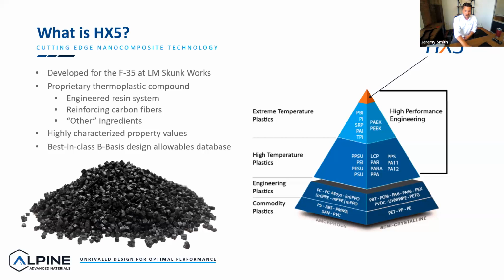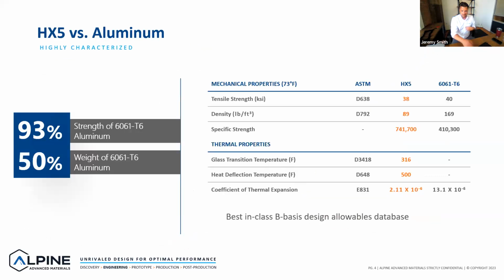But when you compare it to other high performance thermoplastics, it sits near the top for extreme temperatures and at the highest end of mechanical performance. To put some data to that claim, pound for pound, it has about 80% higher specific strength than 6000 series aluminum, which, when this was set out to be developed, the goal was to replace for lightweighting purposes, but also for higher durability in salt fog environments, and in hot and cold environments. Over its thermal cycle, it is a lot more stable than aluminum or any other thermoplastic or metal material. Its coefficient of thermal expansion is 1/6 that of aluminum, so it's extremely thermally stable across its thermal cycle.